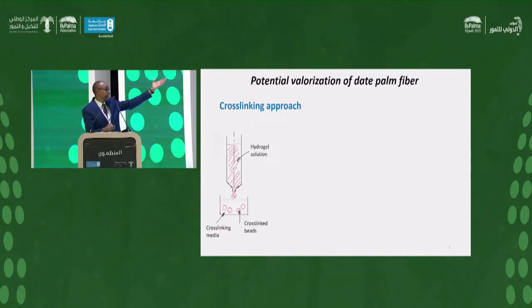The cross-linking: when we produce the bead from hydrogel, we have the cross-linking media, and we have the bead before cross-linking. The size depends on the surface tension and the configuration of the system. And we can obtain the cross-linked bead, which can also be used for different treatments, because we have ultra porous materials.